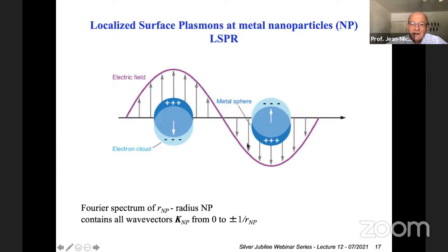But there is a second effect, which is seen when we monitor the transmission of a sample of nanoparticles, which is scattering. And the scattering increases like the square of the volume of the nanoparticles. So the bigger the nanoparticles, the larger the scattering is.